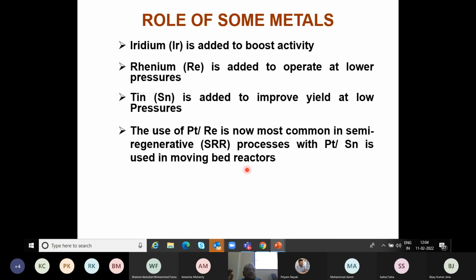How it physically helps you is that suppose you have two platinum particles, and there's a rhenium or tin sitting in between. It helps you to break that carbon bridge that can get formed between two platinum particles. So it breaks that, and it helps you reduce the coking. And the more rhenium particles you put, the less is the coking, and vice versa. So this is called a skewed catalyst. More rhenium and less platinum.